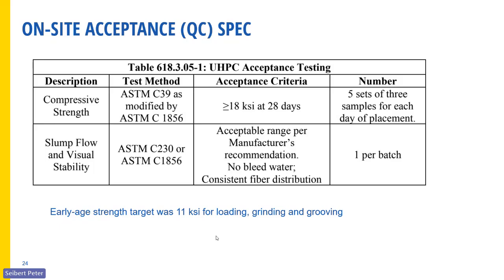As the material is being produced from the batch plant, delivered and placed in front of the paver, it has to be smooth. But also throughout the day, there's a lot of changes in temperature, humidity, light, sun, and we've seen that. So what we had is we were then working with the supplier to adjust the mix within the ranges to ensure that the hardened properties are met. Therefore, the flow test was very important to validate this.